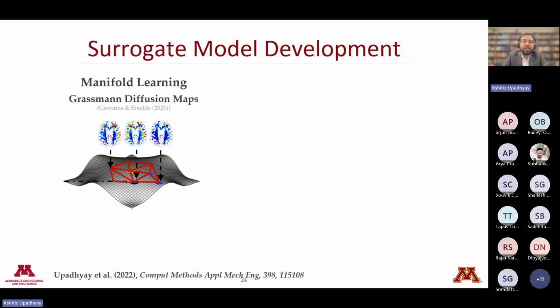So for reducing the dimensionality of the output, we use this method called Grassmannian diffusion maps, which was invented by Dimitrios Giovanis and Mike Shields of Johns Hopkins in 2020. This method is a two-step dimensionality reduction method. The first step, the full output, so in this case, the full strain fields, are projected down to a Grassmannian manifold using thin singular value decomposition, which is a linear dimensionality reduction. And the next step, diffusion maps, is run on the reduced data from the first step.